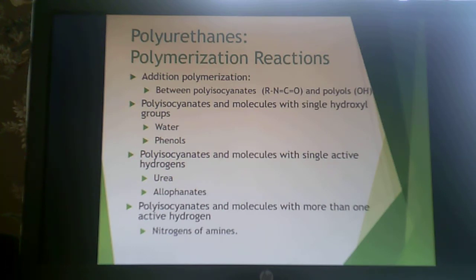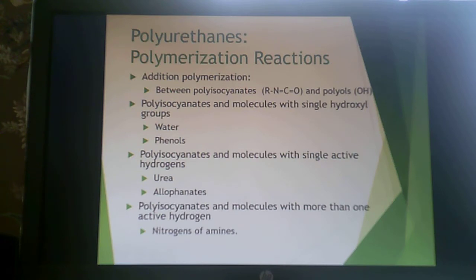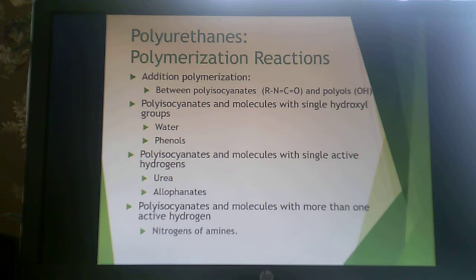This polymerization is a weird exception to the rule — it acts like a condensation in how it builds molecular weight, but you don't condense out a small molecule. Polyisocyanates will react with molecules containing single hydroxyl groups like water or phenols, molecules with single active hydrogens like urea or allophanates, and molecules with more than one active hydrogen like the nitrogens on amines. The take-home message is that polyisocyanates will react with pretty much everything you put them near — the challenge is getting them to react the way you want.